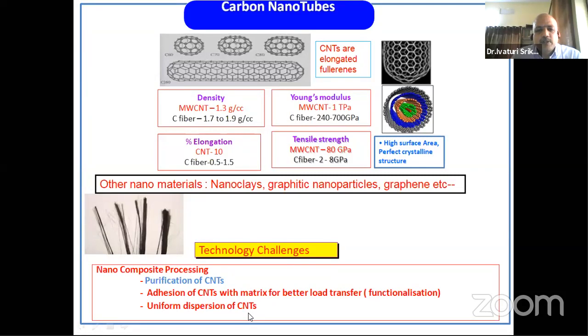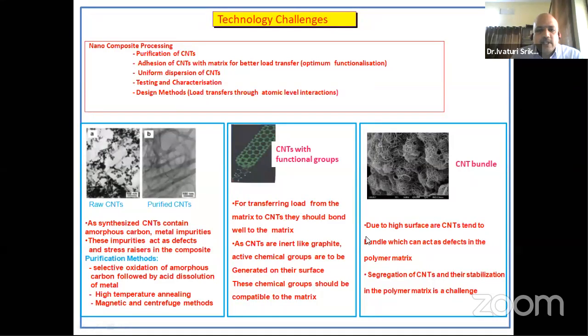But people realized that this was the kind of view in 2005 to 2010. People were of the opinion that if we can solve certain technical challenges in the area of nanotubes, like purification of nanotubes, as synthesized nanotubes are not pure, then improve adhesion, meaning if you want to use them as a reinforcement, it should bond well with the matrix, and then disperse them, as generally they come with high agglomeration, if you can disperse them properly, probably we will hit very high properties in terms of nanocomposites. So that was the motivation for the research. This is the same thing I showed in the previous slide: purification, functionalization and dispersion.